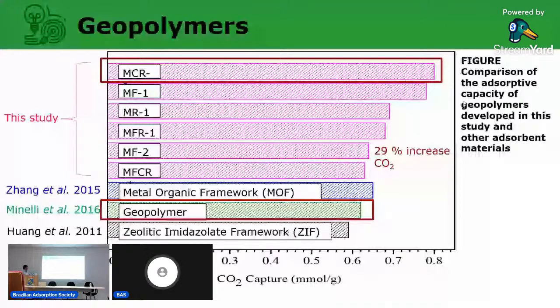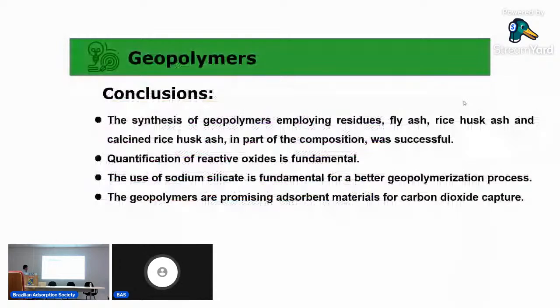The main conclusion with geopolymer is that the synthesis of geopolymer employing residue fly ash and calcined rice husk ash in part of the composition was successful. Quantification of reactive oxide is fundamental. The activator is sodium silicate, the main one, and these geopolymer adsorbents are promising adsorbents for carbon dioxide capture.